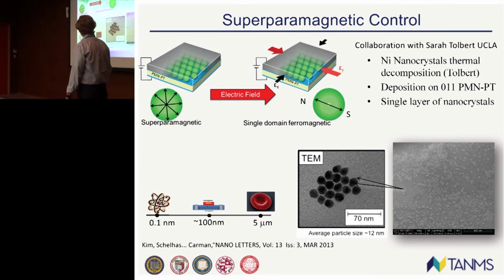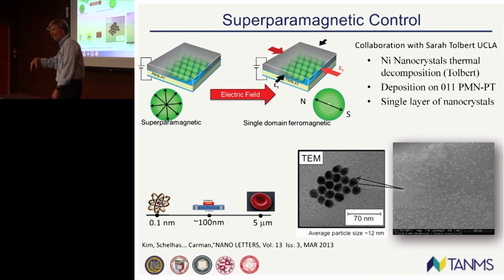Now guys, this is a TEM image, and in our test sample, the particles are not this close. Remember those little ligands I told you about that the chemists can put on the particles? They put ligands on these particles to make sure the particles were at least 2 diameters away. Why am I telling you that? You don't want dipole-dipole interaction. You want to keep them separated.